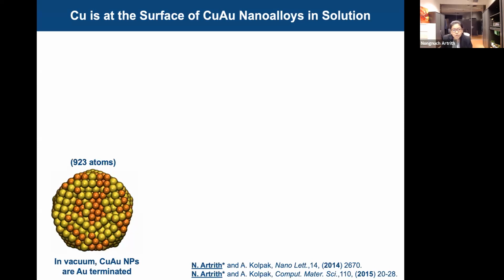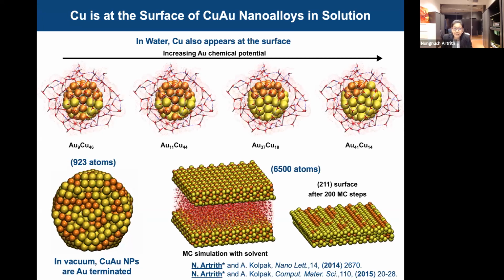And not only that, we could also extend our database by including, for example, in this case, copper in solutions. So we include more chemical species like water to demonstrate that it also can simulate nanoparticle in solution. You can see that there are so many different compositions, and the output after we do simulation also show different results from in vacuum.